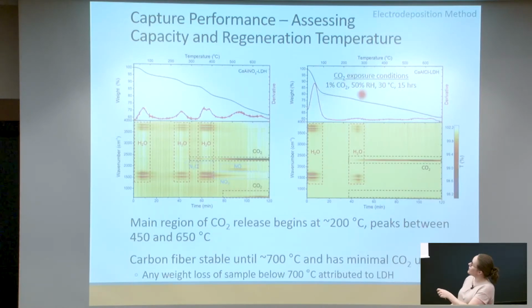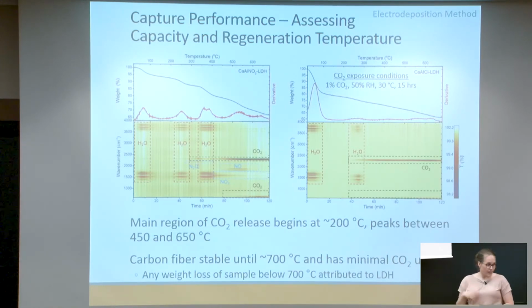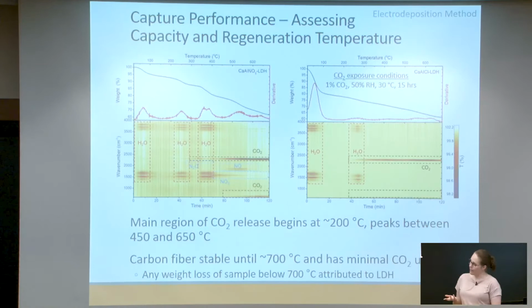So we want to understand, we've made this material, how does it behave in terms of CO2 capture? And so one thing that we can do is, after we've done the capture itself, these are the conditions that we use for capture here, we can heat the material up, watch how much weight it loses as you increase the temperature. And so that's what's shown on this diagram. In the grey, the red is the derivative of the grey. And down here is actually infrared spectroscopy data that shows us what type of gas molecules are being lost at which temperature. And so this is how we can work out exactly what temperature is required for regeneration through these signatures of the different gas molecules being lost.